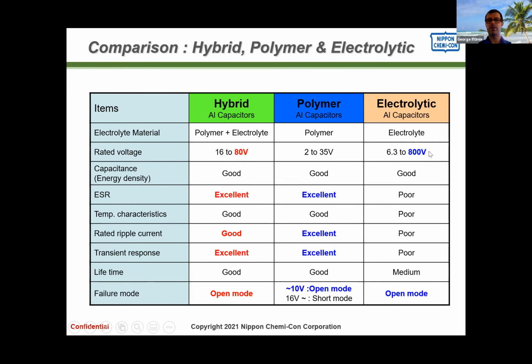Electrolytic capacitors are, of course, available all the way up to 800 volts. And we're trying to make them even higher than that. But the most cost-effective for liquid electrolytic capacitors is roughly 650 volts. Once you exceed that, ESR of the 700 volts and above capacitors is very, very high due to the internal arcing that will happen inside the capacitor itself.